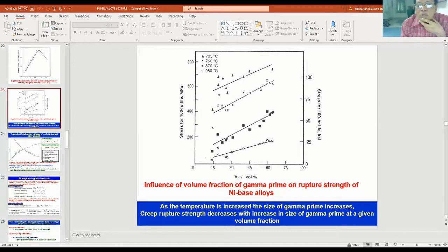On increasing the temperature, you can see that the creep rupture strength is coming down. Though to a certain extent, with increasing volume fraction of gamma prime, creep rupture strength is increasing. That means that the volume fraction plays a very, very important role. Size plays a very, very important role. Morphology of the precipitate plays a very, very important role.